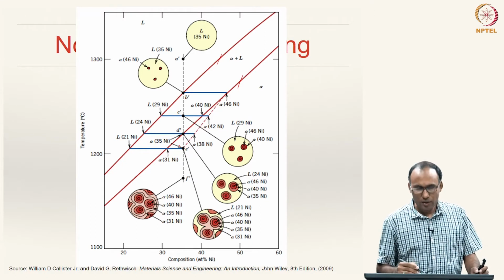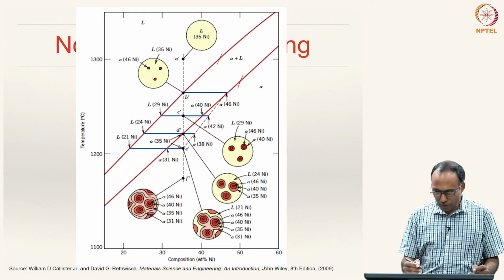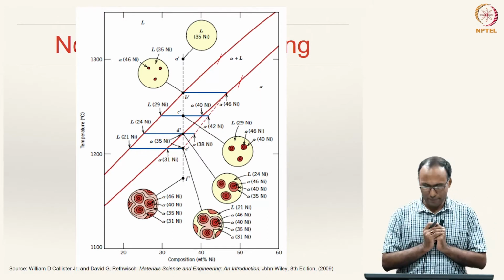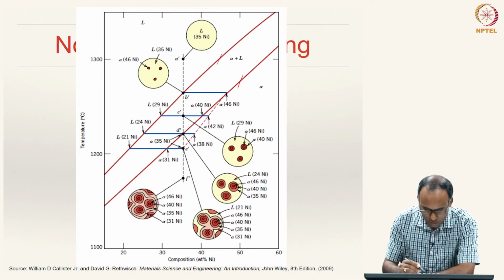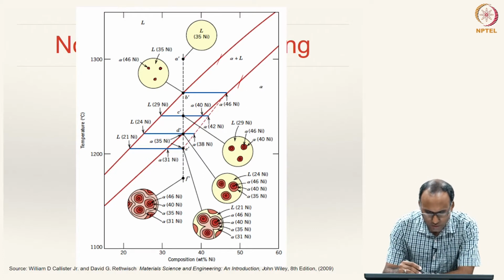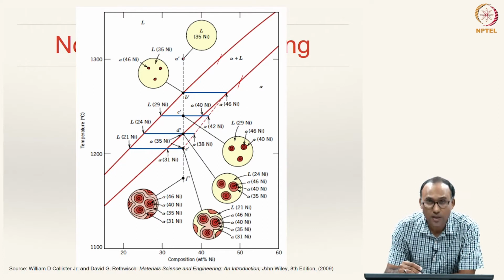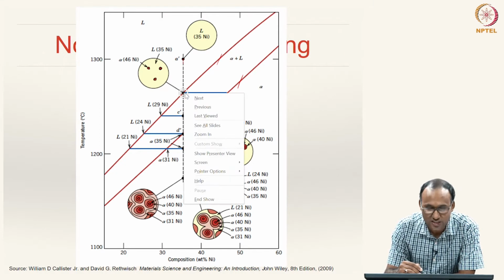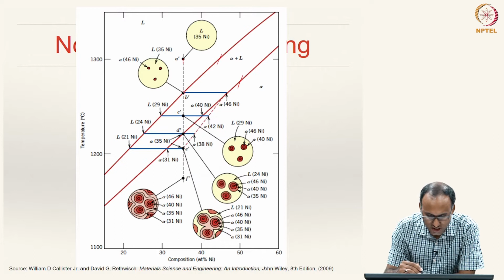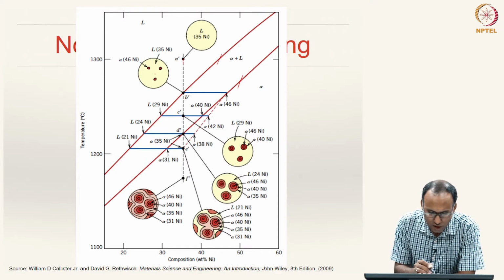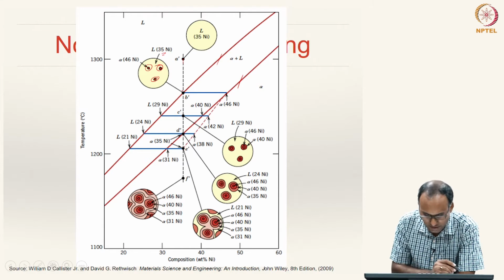So, now the microstructure should evolve according to this. All right, now let us look at what happens. Now, we have the same 35% nickel alloy. When we are cooling down up to point B, nothing changes because the liquidus line did not change, and again the same small nuclei of solid alpha form, and the composition of alpha will be about 46% and the composition of liquid will still remain 35%.